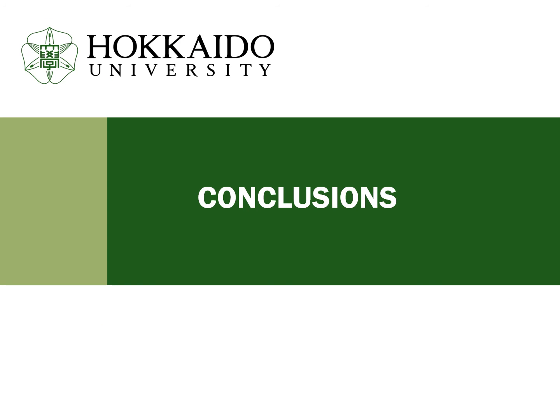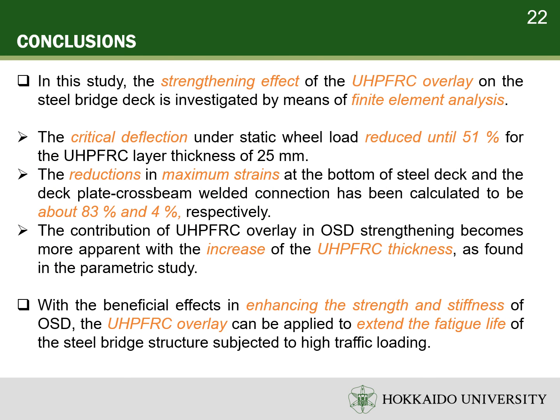Conclusions. In this study, the strengthening effect of the UHPFRC overlay on the steel bridge deck is investigated by means of finite element analysis. The critical deflection under static wheel load reduced by up to 51% for the UHPFRC layer thickness of 25 mm. The reductions in maximum strain at the bottom of steel deck and the deck plate cross beam welded connections have been calculated to be about 83% and 4% respectively.